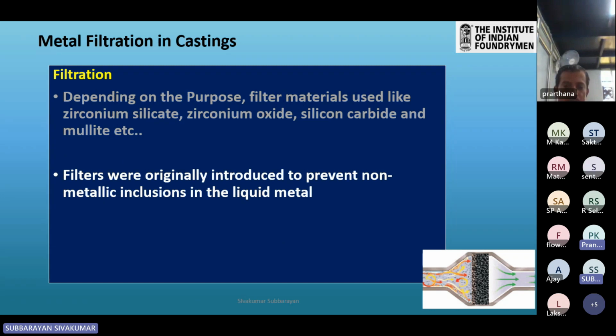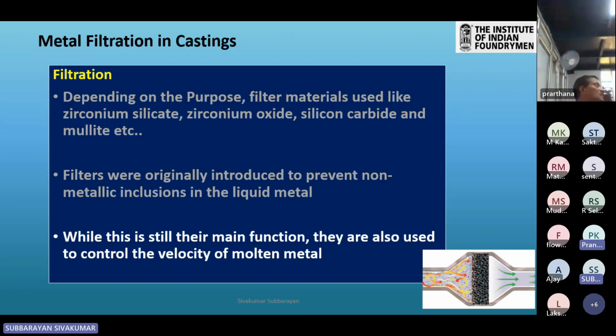Filters were originally introduced to prevent non-metallic inclusions in the liquid metal. When the concept of filtration evolved in the foundry industry, maybe 10 or 20 years back, the original intention was to filter out the non-metallic inclusions. Later on, a lot of research has evolved in the filter manufacturing industry, and while this is still their main function, they are also used to control the velocity of the molten metal. When the metal enters the running system, up to the point of the filter, it can be a turbulent flow, but once it crosses the filter,